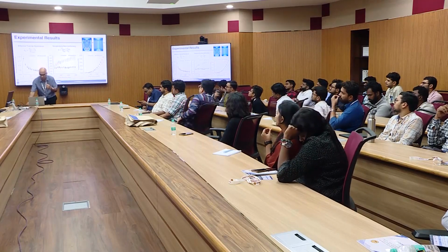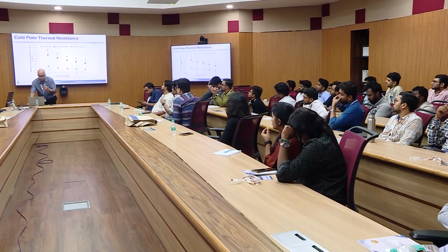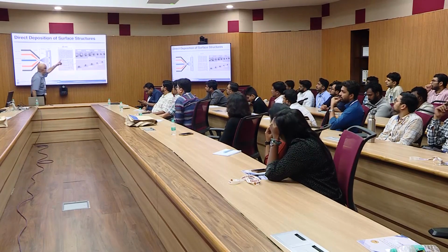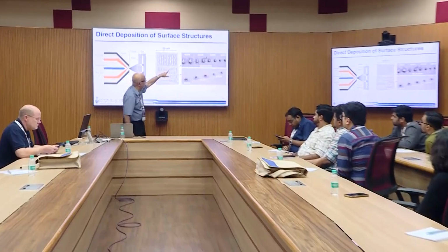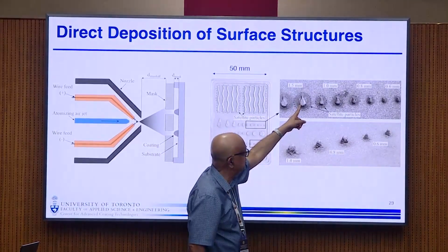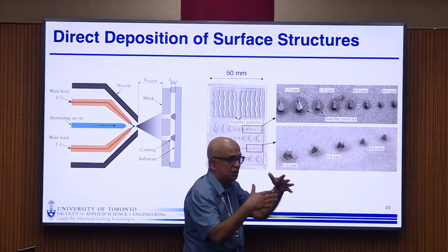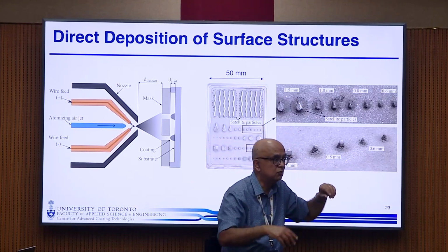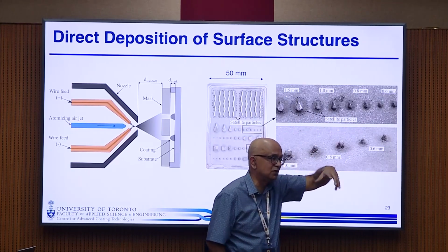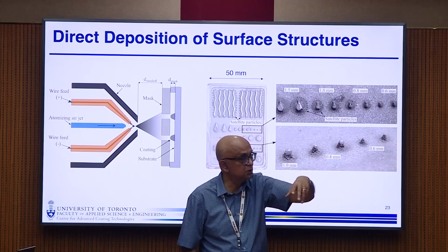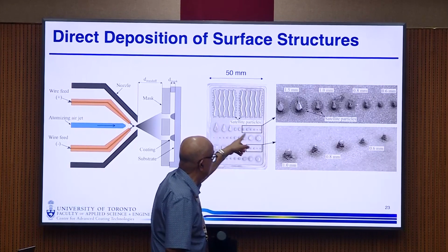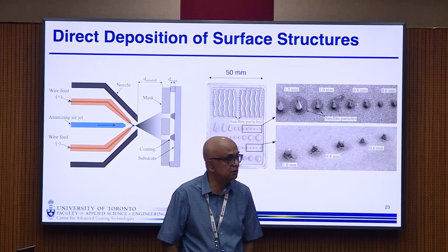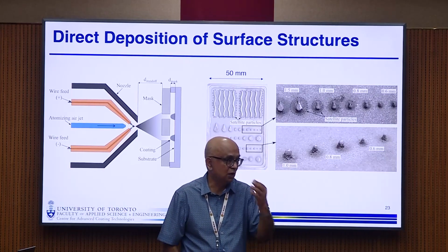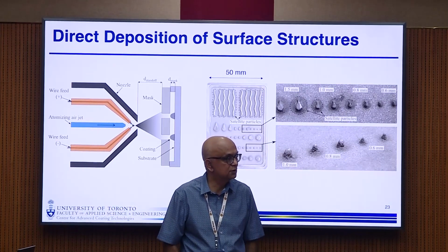This is the one which I showed over there, and we were trying to see how fine you can go and still retain the shape. Down to about 1 millimeter, after that it really becomes difficult. Less than 1 millimeter, you don't really retain the shape because it's a masking process. But for things like channels, or a couple of millimeters in size, you can get the shape quite accurately. Fortunately, for this sort of application, it's not high precision. You just want the liquid generally where it should go.